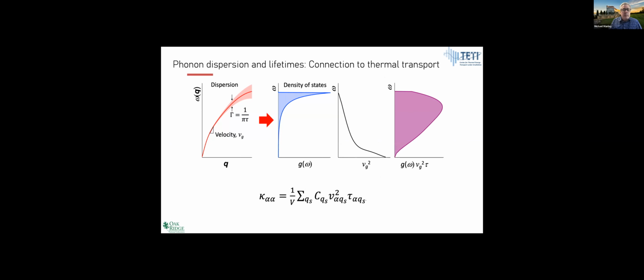I think generally people understand this, but just for illustrative purposes, I have a little cartoon here which shows if you start with a simple acoustic phonon and you try to piece together the parts that you get out of the dispersion curve, you can get, of course, group velocities from the slope, you can get lifetimes from the width, and from that you can also get a projection of the density of states, which is related to how much heat is carried per mode, per section of the branch. Then you can multiply these all together and you get something that gives you an idea of where the thermal conductivity lives in the curve, and it kind of lives over the entire curve. You can't just look at the edges of the curve. So you really need momentum resolved inelastic scattering, whether it's with X-rays or neutrons.